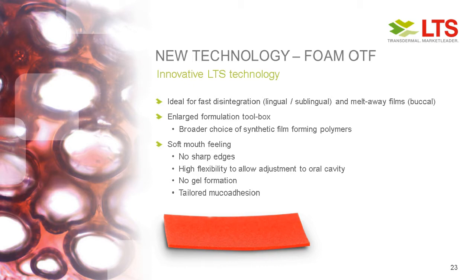So we have a much broader choice of synthetic film-forming polymers, which usually, without the foaming technology, would disintegrate within, I don't know, minutes, 10, 20 minutes maybe even. And by using the foam technology, we can decrease the disintegration time significantly. Also, the thin films have a significantly improved soft mouth feeling. They don't have sharp edges. Even on this picture here it looks like edges, but they're really soft. So they're highly flexible and allow an adjustment in the oral cavity, especially if they're used in a